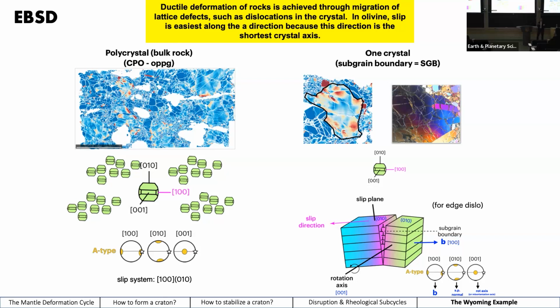We have predictable ways that it can slip. And so we can actually look at individual olivine grains and measure things like the subgrains, which are basically the same process of dislocation creep happening, but on one grain. And if we can pinpoint what that subgrain boundary is doing, we can actually infer a slip system for that grain.